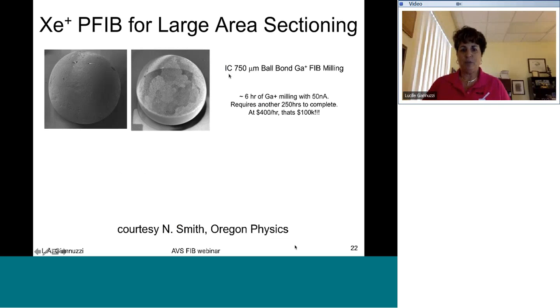So this is an example from, again, Noel Smith at Oregon Physics. This is an IC pad ball bond, 750 microns. Gallium FIB milling, 6 hours of gallium milling with 50 nanoamps, and basically barely tickled the surface. This would require another 250 hours to complete. If you take a commercial rate of $400 per hour, that's $100,000 just to cut through this ball bond using gallium FIB.